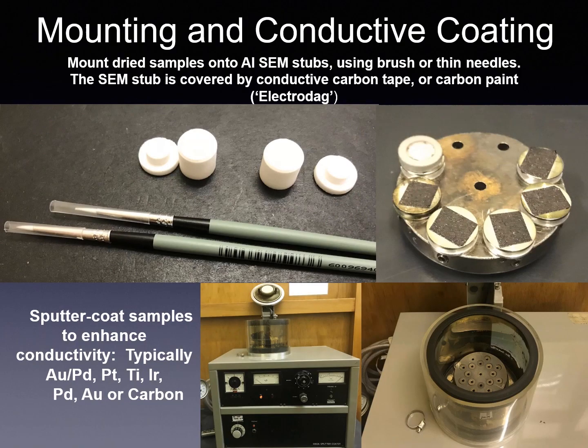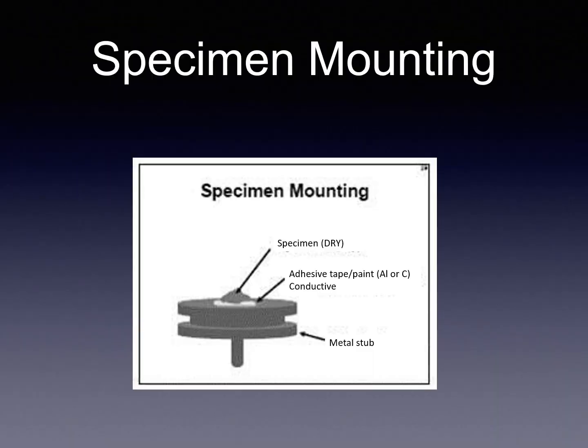Sample mounting and conductive coating. Mount dried samples on an aluminium SEM stub using a brush or thin needles. The SEM stub is covered by conductive carbon tape, carbon paint, or Electrodag. Sputter coat the sample to enhance conductivity, typically with gold, gold palladium, or any other metal or carbon.